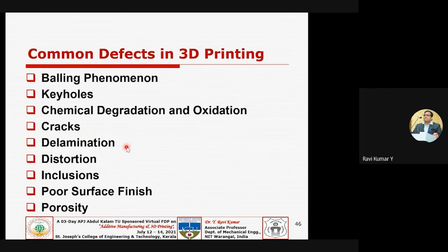It may be from the substrate to your layer, or among the layers, where your layers get delaminated, maybe because of shrinkage or warpage, or even distortions also we can find. Because of these issues, the temperature gradient or the internal, residual stresses have developed within the layer or at the interface of two layers, and so on. And you can find some inclusions and poor surface finish.